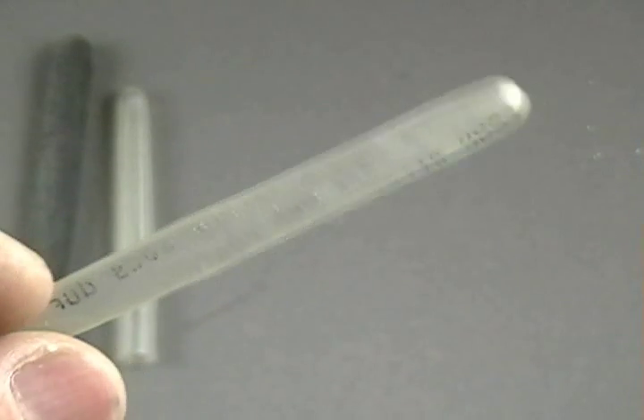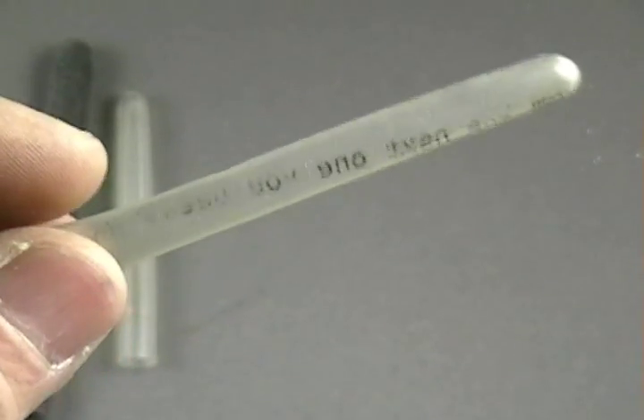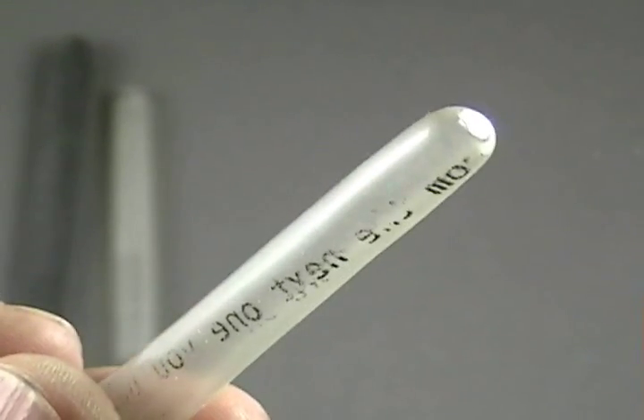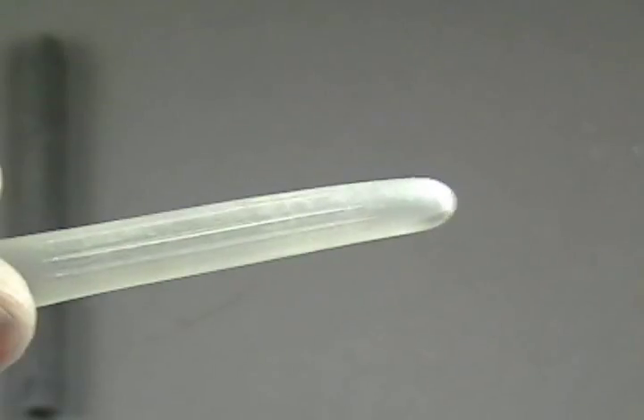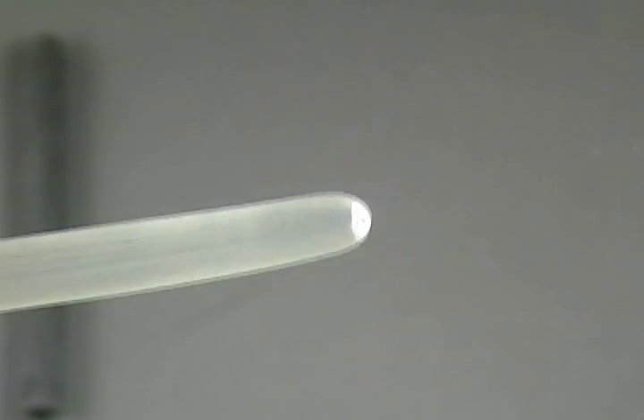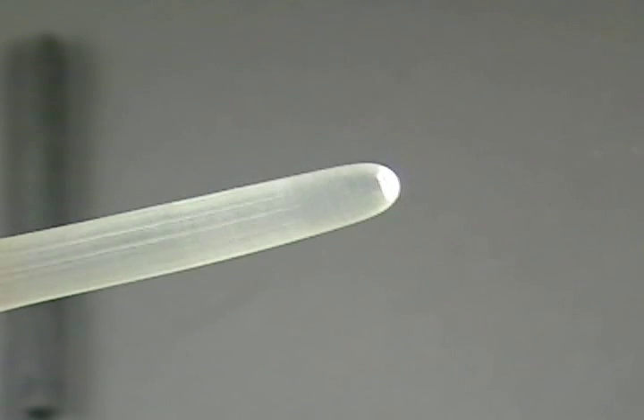The next sack up is widely sold as silicone, but it's actually PVC. A few days in an envelope was enough to leave it permanently flattened and distorted. The material is so full of reactive plasticizers that it dissolved the writing right off the paper in which it was enclosed — that's why it looks like it's been printed on. Note that the sack is thicker at its tip, which is a giveaway that it was dip molded and not injection molded. You can see the same drip at the tip of this reproduction Parker 51 sack, which is also dip molded PVC. PVC is okay for sacks in metal housings, but don't use PVC where the sack is in direct contact with a celluloid barrel. Over time, the PVC's plasticizer will migrate into the celluloid and can turn it soft and gooey.